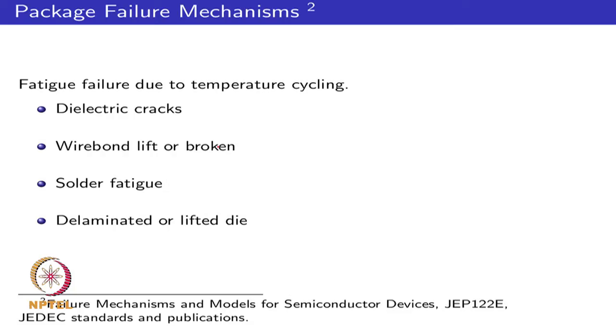You would have stress buildup across layers because of your thermal characteristics, and you might have cracks in your dielectric, as different points of the dielectric might expand at different rates. Wire bonds used to attach the chip to your external terminals, typically silver or aluminium, might have a different expansion coefficient. They might break or lift off. You have solder joints within the module, and those points would develop fatigue. Your chip itself might get delaminated from the bottom. Your insulation might get delaminated from your base plate, and you might end up with lifted dies.